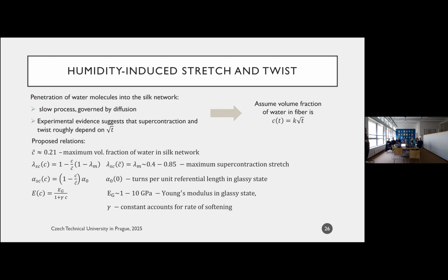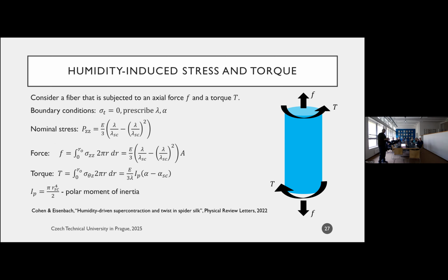And after we had this, we said, okay, so now the supercontraction stretch should look something like this. We assume that it scales linearly with the amount of water in the fiber. The supercontraction twist also scales linearly with the amount of water in the fiber. And the Young's modulus scales as inversely proportional to the amount of water. And once we had this in mind, we were able to talk about boundary value problems, right? Now we have everything we need, so we can define a boundary value problem.